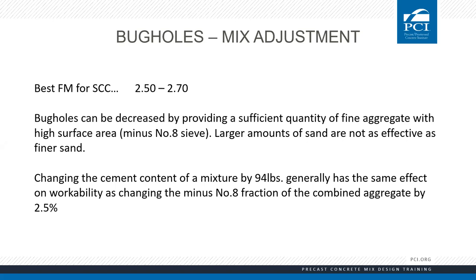The result that's cheaper and more effective is having control of your aggregate. Selecting a finer sand in the range of 2.5 to 2.7 FM is going to be more impactful and cheaper. Even if we pay more per ton for that sand, it's still going to be cheaper than 100 pounds of cement. As I started the presentation yesterday, when troubleshooting or building a mix from scratch, we always start with aggregate. If I'm troubleshooting bug holes, first thing I look at is aggregate.